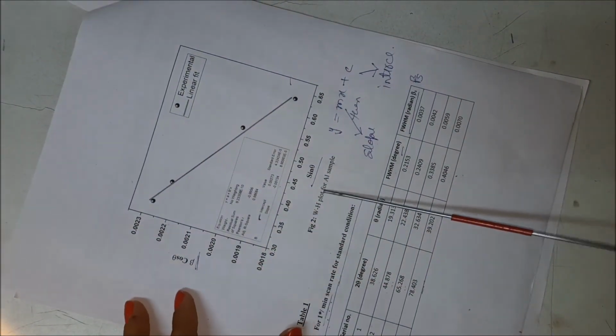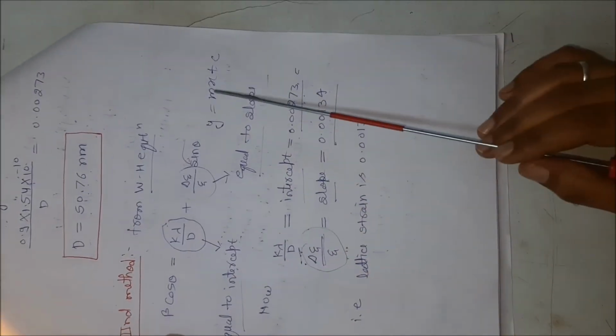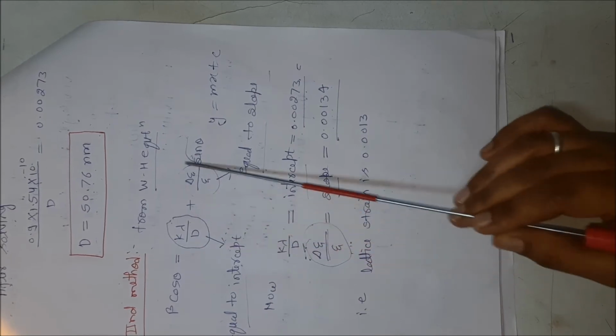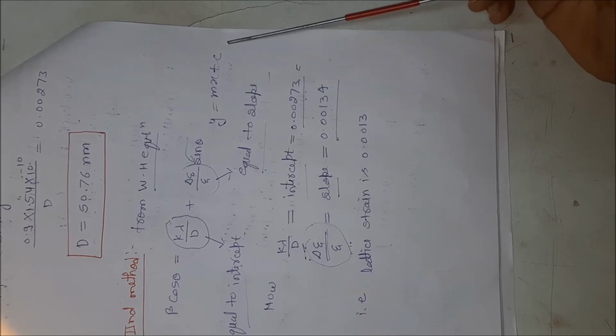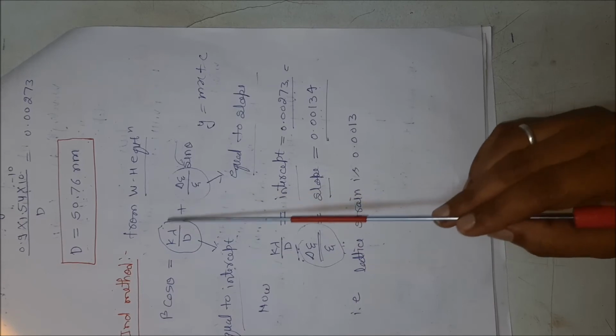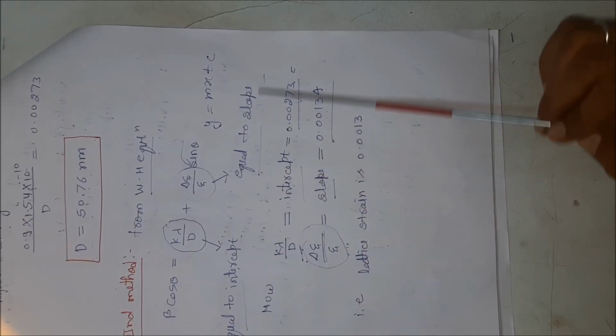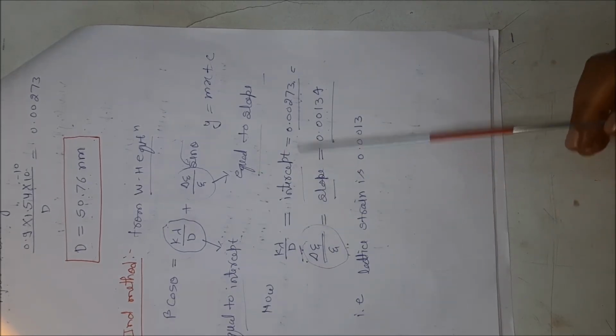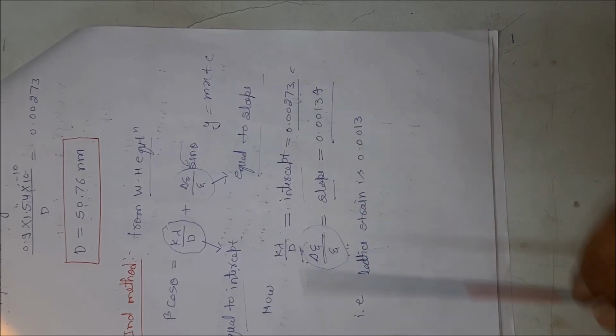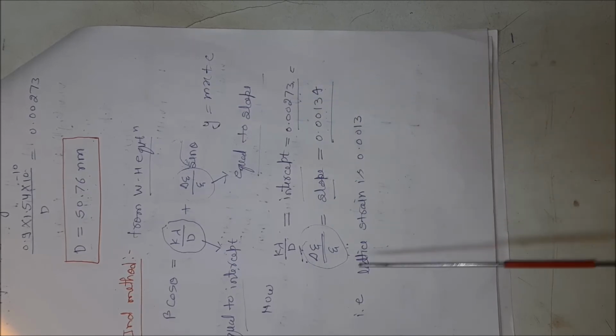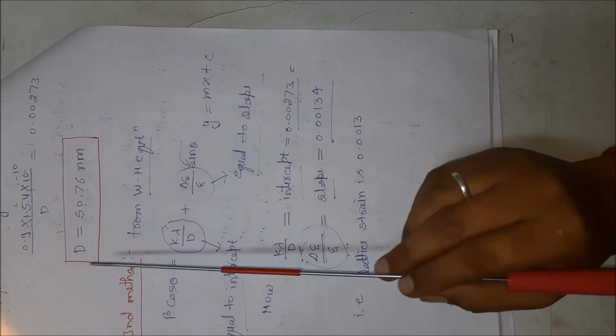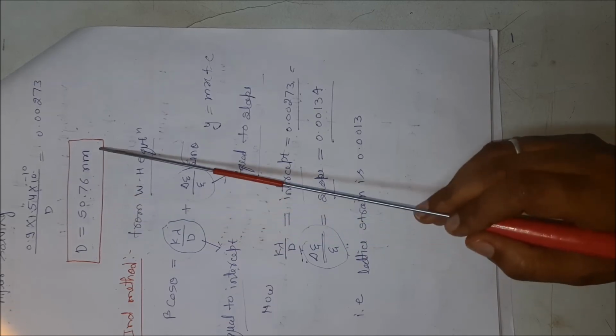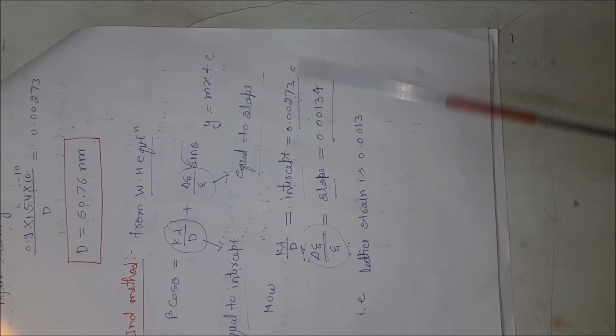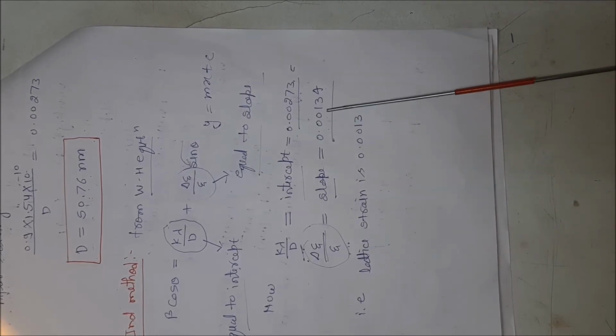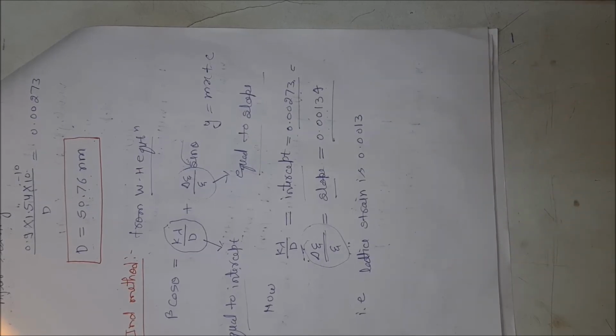By using this graph of beta cos theta versus sin theta and the Williamson-Hall plot equation, which is beta cos theta equal to k lambda upon d plus delta d upon d sin theta, and comparing with y equal to mx plus c, the linear equation, k lambda upon d is equal to the intercept and delta d upon d is equal to the slope. The intercept obtained from the curve is 0.00273. After putting the value of k lambda, we get the value of d, which is 50.76 nanometer. After that, we compare delta d upon d, which is equal to the slope, 0.00134. This means that the lattice strain is 0.0013.